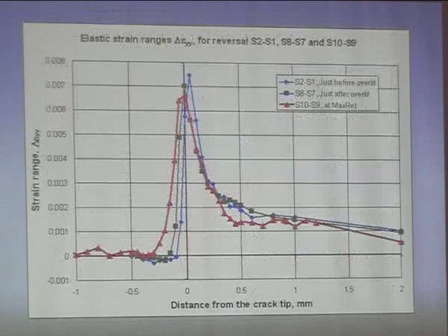And in order to see further that in terms of stresses and strain ranges there are some changes from here to there, you see very clearly that the change in strain is significant because it's on the almost flat part of the stress strain curve. So what we are saying is that the elastic strains are almost the same, but does it mean that the elastoplastic strains will be the same? When you look at elasticity, you may see, oh, it's the same range. But if you take the triaxiality into account and plot the stress strain loop, that loop will be much more narrow for the red case than for the blue case.